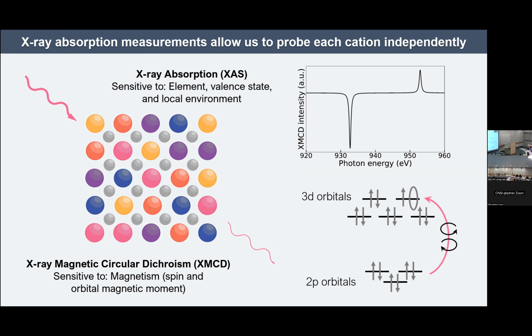And so we can actually calculate the exact spin contribution from every element. The way this works is that the application of a magnetic field to the sample splits the spin up and spin down states by some amount, and you more preferentially have one process versus the other. And so an XMCD signal, a typical one, may look like this if the moment is aligned with the field.